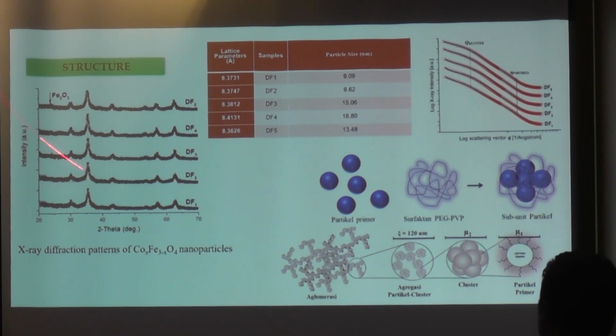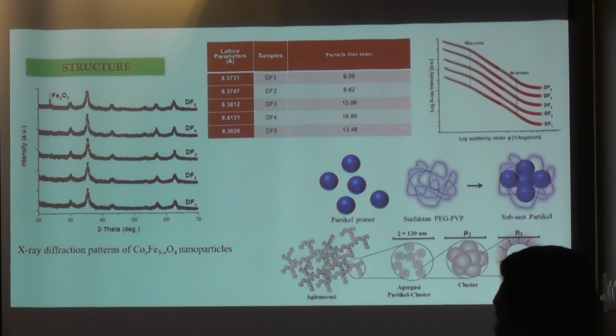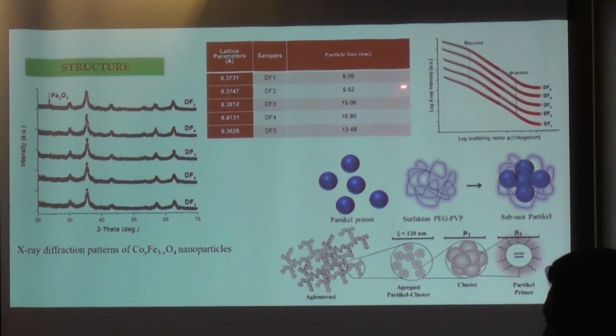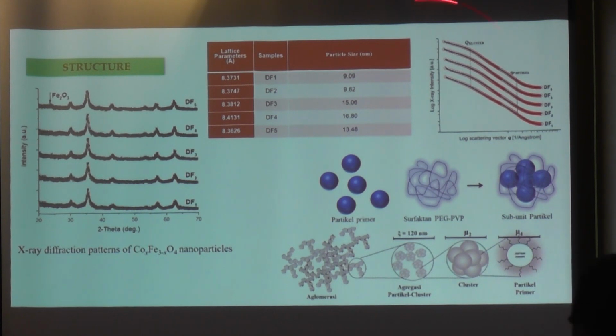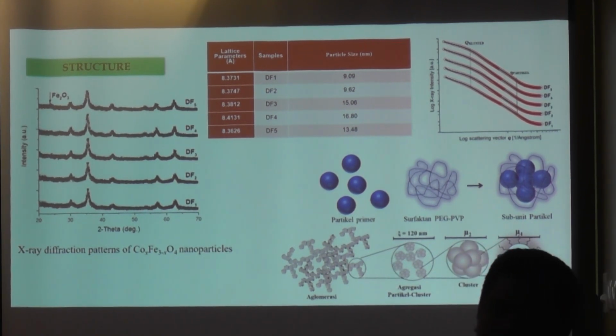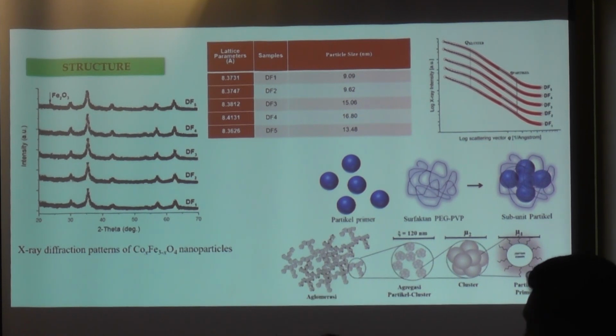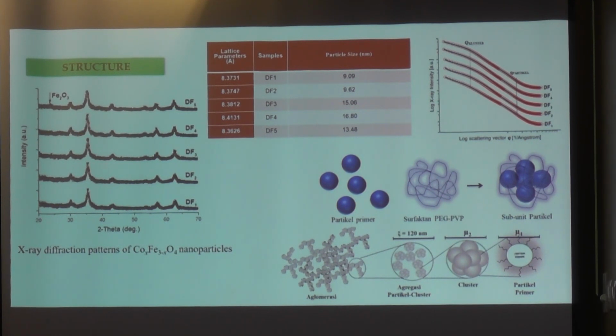For hierarchical structure, we characterize this sample using synchrotron small angle scattering. The data looks something like this. If we look at this data, it is quite similar. But if we fit the data using a high precision method, using a mathematical approach, we can obtain the hierarchical structure. We know that magnetic nanoparticles, especially in ferrogel and ferrofluid, in magnetic fluid, consist of building blocks, something like this. The building blocks make a second, bigger cluster, something like this.